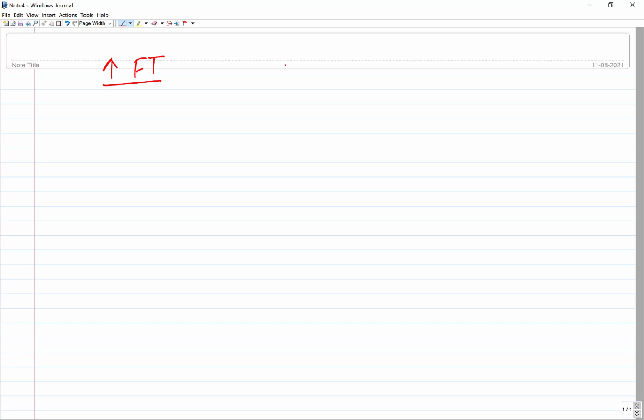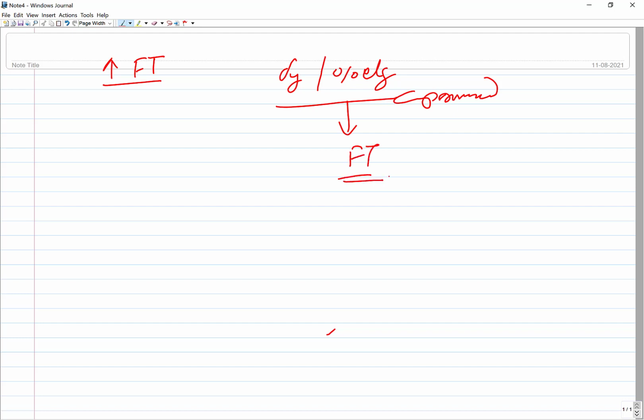But when you perform the welding or joining inappropriately, using poor joining conditions, then both yield strength and ductility, percentage elongation, or either of them, are compromised. And if either of the two is compromised, your fracture toughness is compromised. Then certainly your tolerance to discontinuity is compromised. Earlier your joint was able to tolerate say 8 mm. Now it can tolerate just 4 mm or 3 mm size discontinuity for given loading conditions, and beyond that it suddenly fails in a catastrophic manner.